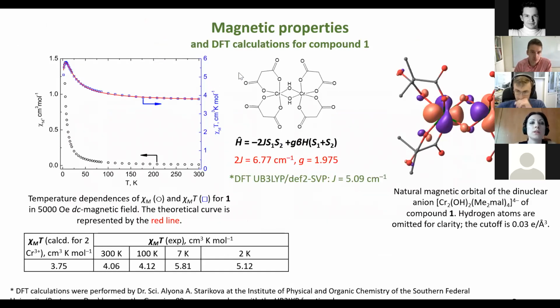According to DC magnetic measurements for compound 1, the χT value at 300 kelvins is in good agreement with the theoretical value for 2 isolated chromium ions. In the temperature range from 300 to 7 kelvins, the χT value increases, but below 7 kelvins, a sharp decrease in χT value is observed. The theoretical interpretation of the experimental plot χT versus T gave the following best fit parameters.